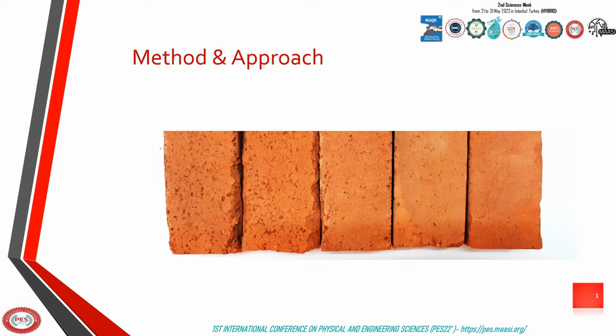We have made the brick samples by varying the percentage of additives and red clay. Samples with 0% biomass additive were made to compare the impact of the biomass additives incorporated in the bricks. The bricks were baked in an electrical oven up to 1050 degrees C. We will focus today on presenting thermophysical results of the samples and comparing 0, 5 and 20% of biomass additives.